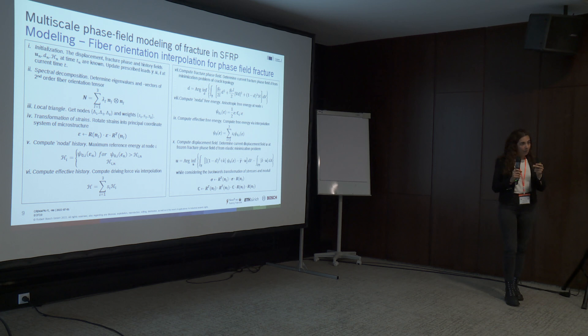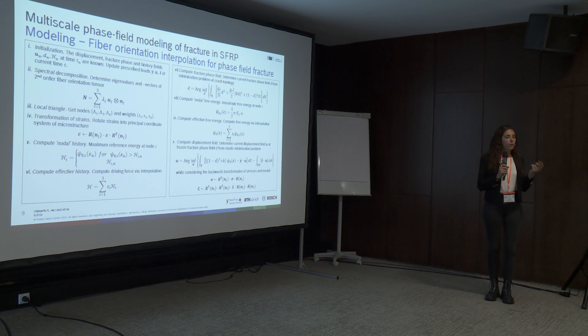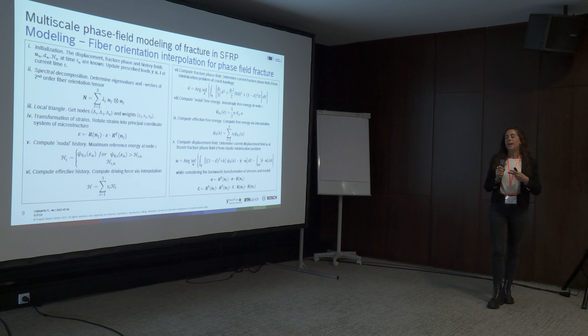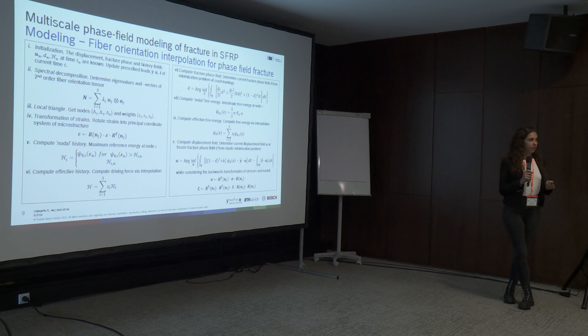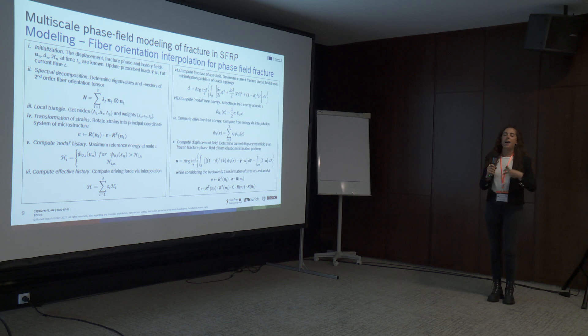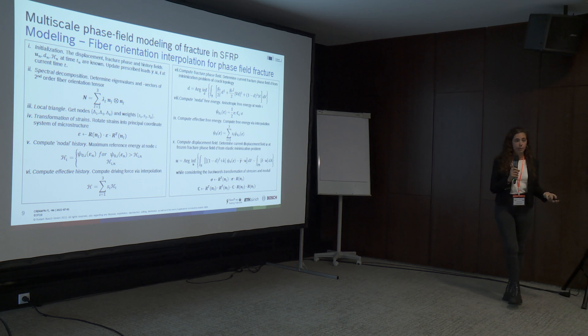This is the full algorithm. In the initial step we initialize and update all conditions including the load. Within each element we perform the spectral decomposition of the fiber orientation tensor, locate the microstructure within the triangle, retrieve the nodes and weights, and by linear combination obtain the deformations. We transform strains into the local coordinate system, compute the nodal history variables and driving force via interpolation, then compute the fracture phase field and the effective energy at the triangle nodes.